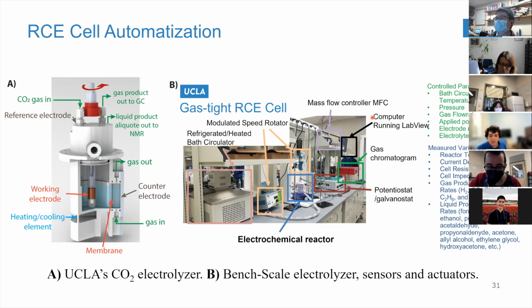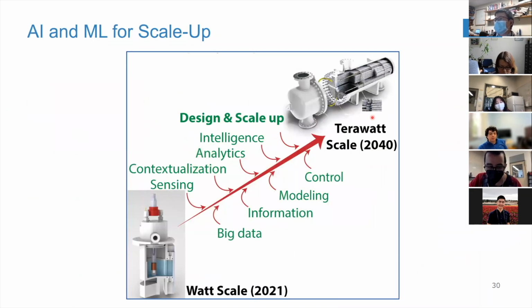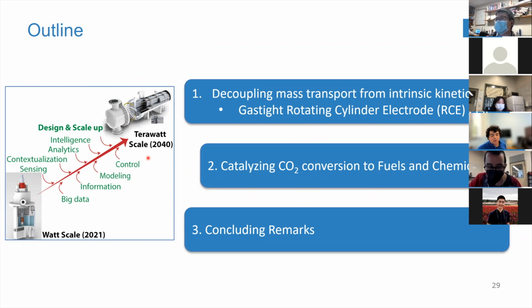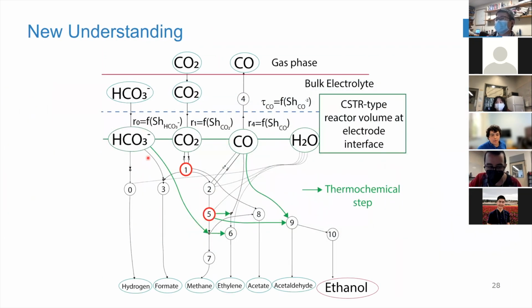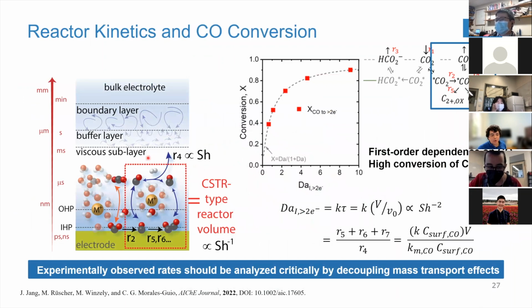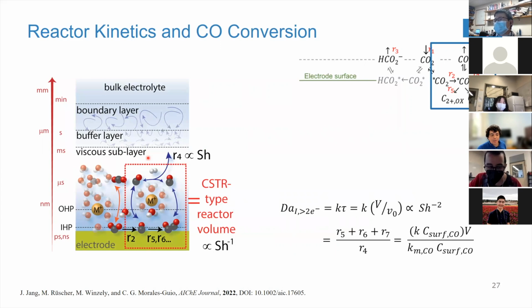So I have a question about the catalyst. Here you use copper as a catalyst, right? As I understand, copper is good at producing C2+ products, but not good at converting CO2 to CO. So I'm wondering, if I switch to another catalyst that has different activity, will we expect to observe a different phenomenon in the conversion versus the Da value relationship? Right. So the first thing is that we do think that intrinsically copper is not as active as gold to make carbon monoxide, CO.